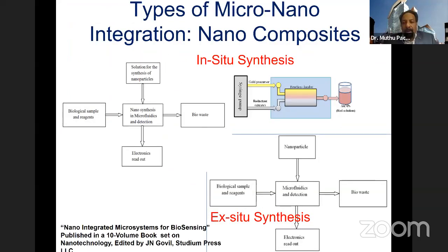So two types of micro nano integrations we talk about, mainly nanocomposites. One is in situ synthesis based nanocomposites, the other one is ex situ synthesis based nanocomposites. In the in situ synthesis based nanocomposites, the nanoparticles are synthesized inside the microfluidics, or sometimes even to make nanocomposites inside the microfluidic channel on the walls of the microfluidics. But in ex situ synthesis, the nanoparticles are produced outside and they're allowed to immobilize onto the microfluidic substrate afterwards. This is ex situ synthesis that's useful for us.